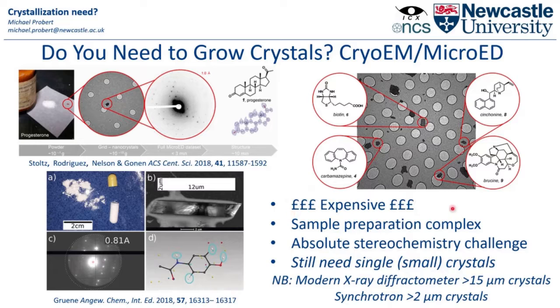It's not without issues. It's much more expensive at the moment. The sample preparation is definitely more complex, and this is even more true for systems that have trapped solvent molecules within the system. Any loosely bound component has to be treated very carefully when exposed to the vacuum chambers that these approaches run under.